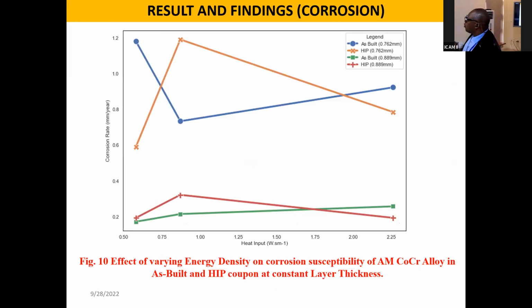So, coming to the corrosion, which is the main essence of the work, we also found out that the corrosion stability of this material, either in high energy basis or in low energy basis, is actually a function of, or depends also on, the thickness. For low energy basis, if the thickness is high, that is 0.8, close to 1 millimeter, the corrosion of this is relatively lower compared to the others. Also, the recommended energy density appears to be even more sensitive to corrosion than the low energy density and the high energy density.